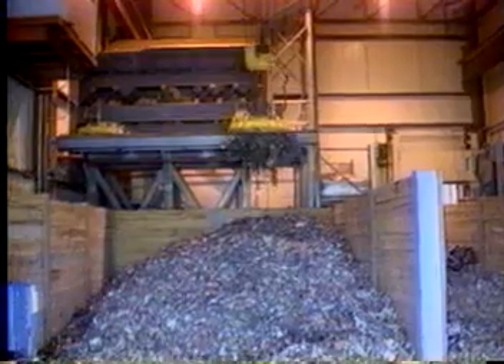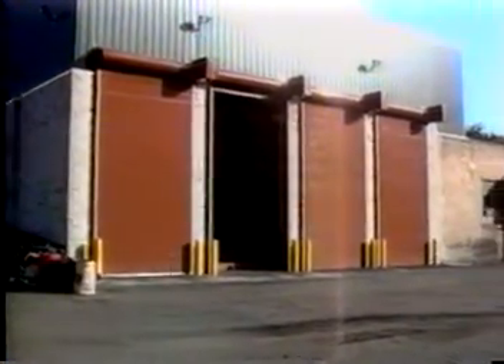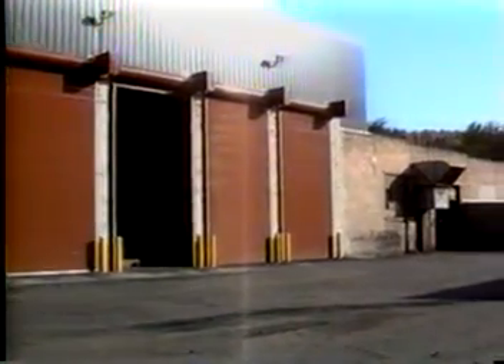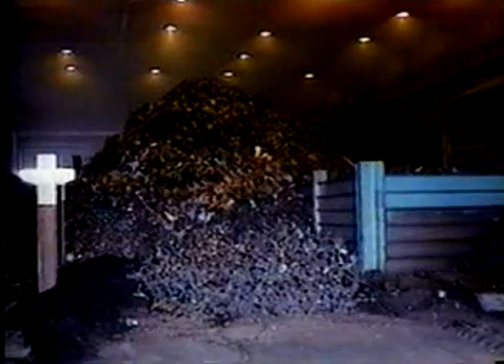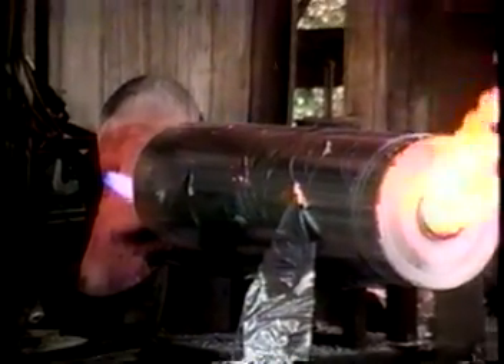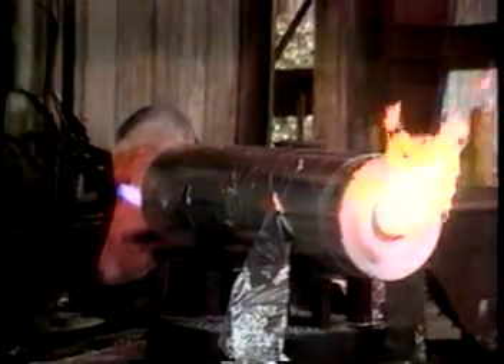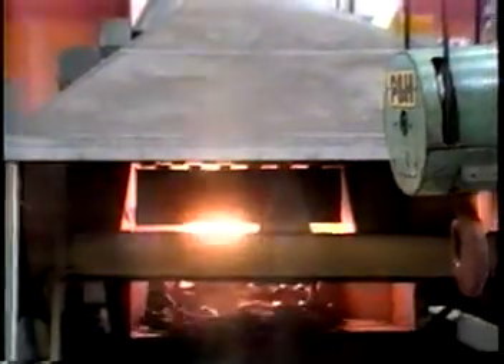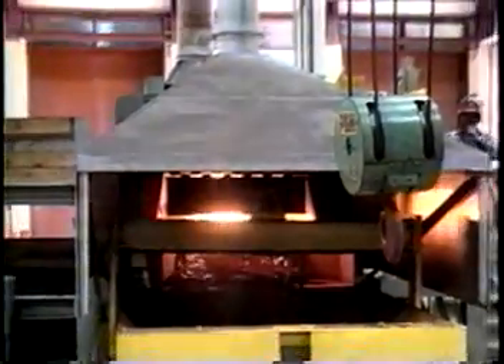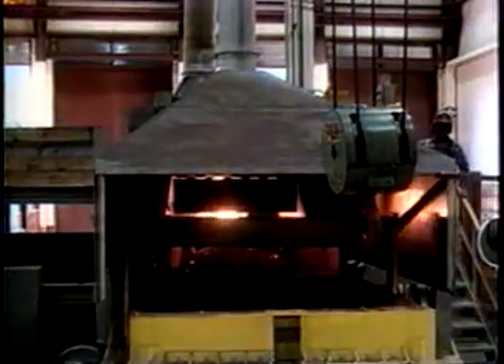In foundries where most of the charge originates as scrap, wet charged materials pose the greatest cause for concern. Some foundries reduce the possibility of water-metal explosions by storing scrap under cover for at least 1 day and then carefully inspecting bales and containers for any residual moisture. But a more reliable solution being used by an increasing number of foundries today is to use both remote charging systems and charge dryers or preheaters.